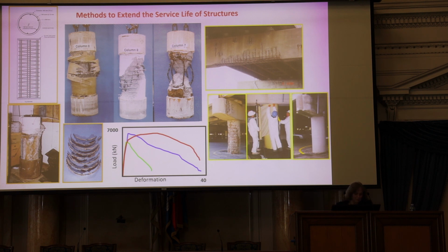This figure here shows the condition of the stirrups after the accelerated conditioning with corrosion. Here are three columns. The first is the pristine column, the column that had not experienced any artificial corrosion. This is a column after being corroded. You see the kind of damage. And here is the column which, after it was dried, very critical to be dried, was wrapped with a few layers of glass FRP.